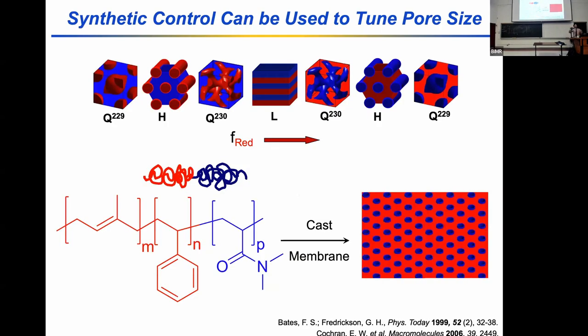But we have one additional handle that we can play with when we think about these self-assembled block polymers. I told you that the thing that determines which microstructure we form is the relative amount of red block to blue block, right? But if I just make a bigger polymer at the same ratio of materials, I should still form the same nanostructure, just with a larger characteristic size, right? So if I have 4 parts of red and 1 part of blue, or 8 parts of red and 2 parts of blue, it should be the same nanostructure, but I should be able to increase the characteristic pore size.